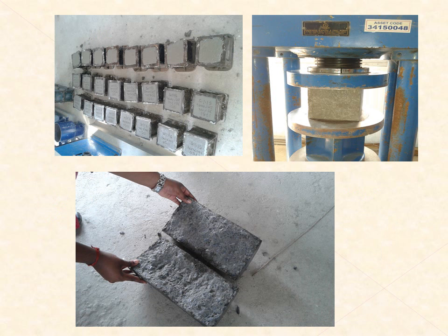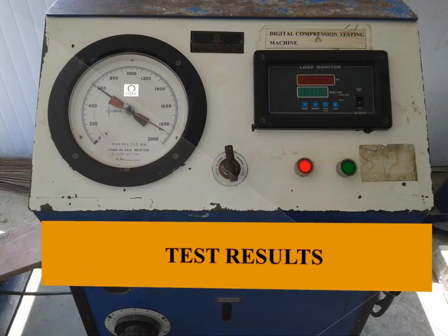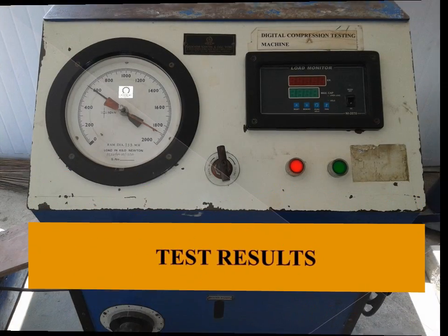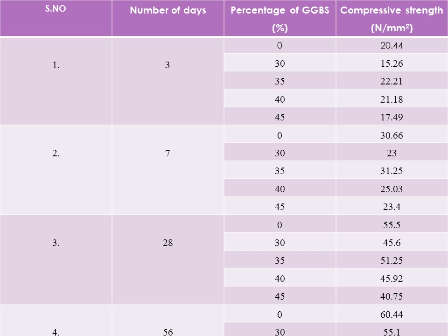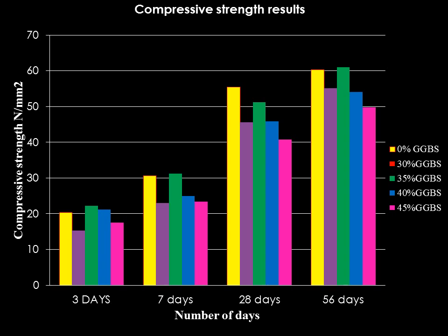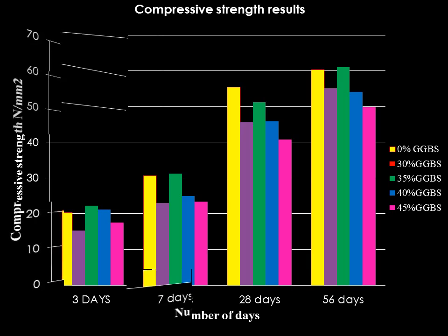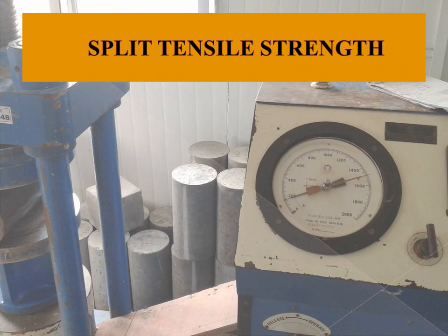These are the photos taken during experiments: cube testing, split tensile strength test. These are the values obtained for 3 days, 7 days, 28 days and 56 days testing. This graph clearly shows that at 35% it gives the optimum strength for 3, 7, 28 and 56 days.